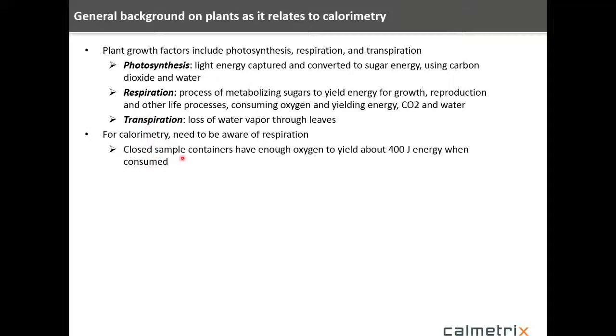And the first point here is that you have to understand that if you're running in a closed sample container, you have enough oxygen in there to yield about 400 joules of energy when it's consumed. So the fact that you do have respiration, you have to realize, are you running in a closed container or are you running in an open container, and what does that mean? So in a closed container, you have enough oxygen to consume about 400 or yield about 400 joules of energy.